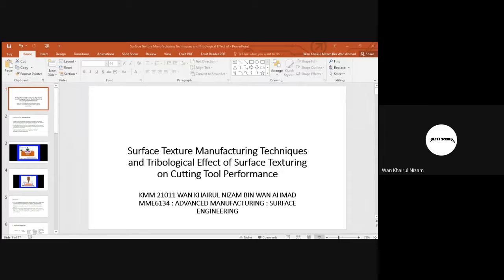So in order to reduce the friction and wear, cutting fluids are often used during the machining process. The two most common conventional cutting fluids are the lubricant and the coolant. However, this cutting fluid only works better at low speed instead of normal speed in turning and milling operations. So to make better cooling, external cooling has been used, such as an external water jet and liquid nitrogen. However, all this kind of cooling only focuses on removing the heat generated at the surface rather than reducing the friction which generates the heat.